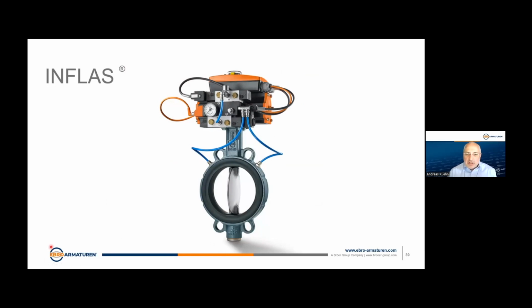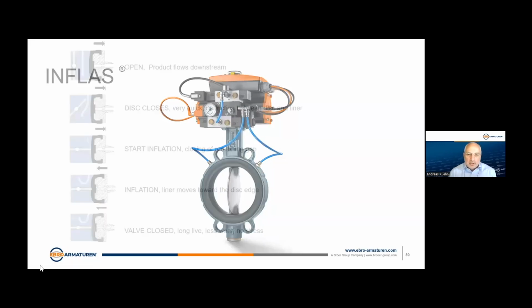That's what I mentioned. You see these hoses again. Here's a butterfly valve that looks a little bit strange. But the main source of contamination is the wear off of the rubber. So you have to seal it off, but there is some rubber. And when the disc squeezes into the liner, into the rubber liner in the sealing, then you might scrape off some particles and those go into the product stream.